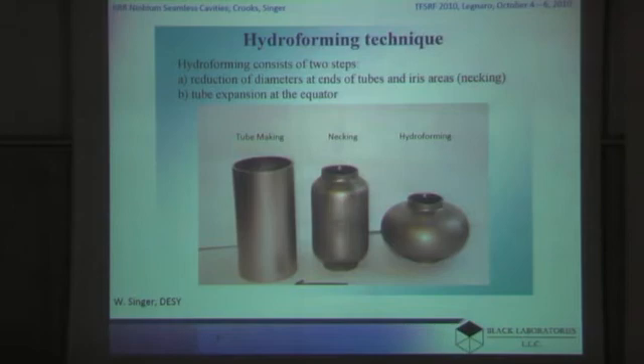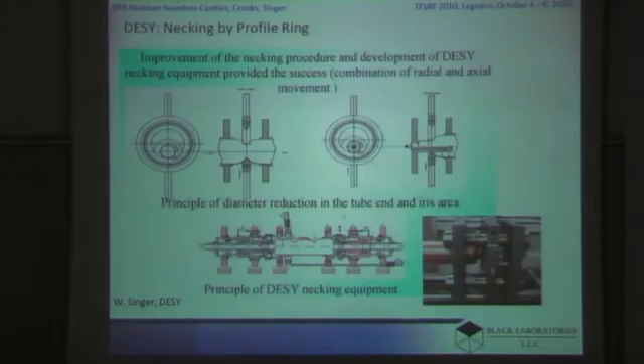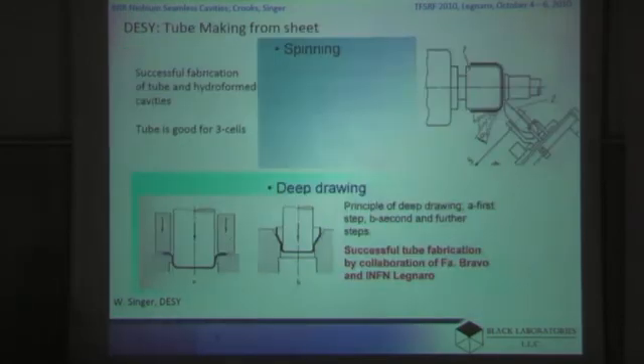The dimensions chosen here were for the ILC geometry of approximately 200 millimeter diameter of the equator region. The two methods of tube manufacture used by DESY involve spinning and deep drawing. The spinning method is to take a sheet and wrap it around the mandrel by spinning the support and then applying an external pressure by wheel. In deep drawing, this sheet is pushed through a die into a tube shape.